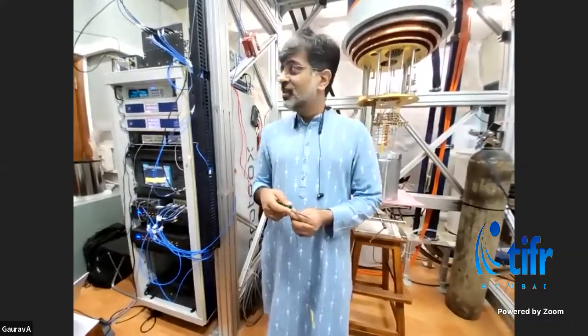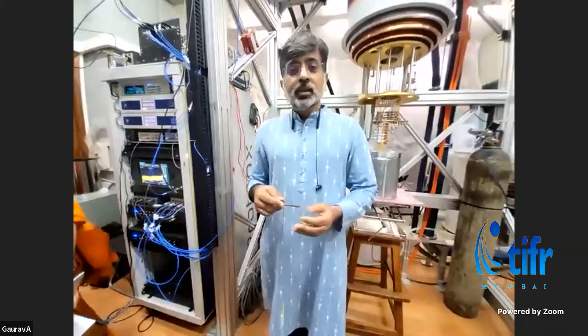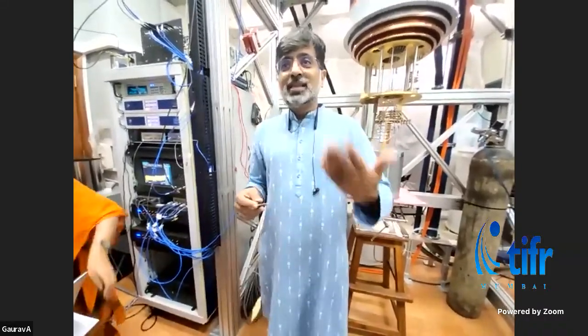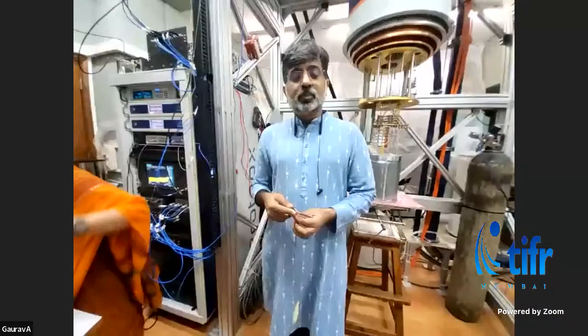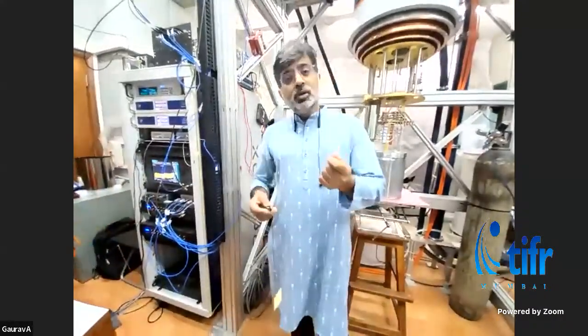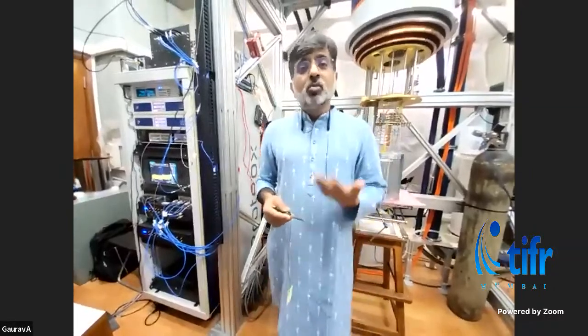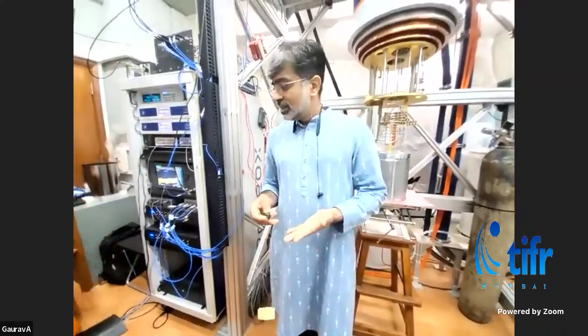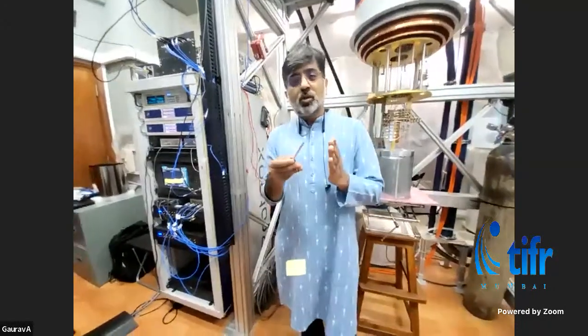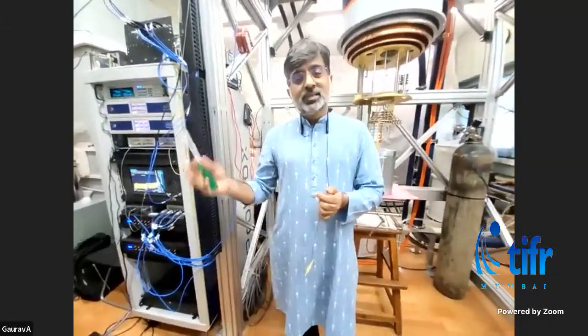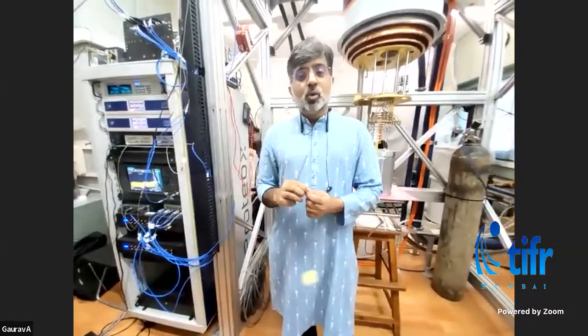And though things have been improving, just to give you a sense, in 1999, when the first superconducting qubit was made, the coherence time, or basically the time scale over which it decayed, was about a few nanoseconds. And now we're already at about 100 microseconds or so. And there have been experiments where people have approached almost a millisecond. This is important because when you're doing your computation, you don't want the system to decay, because then the computation is essentially garbage. So right now, the experiments have to be done in a very, very short amount of time compared to the time over which these systems decay. That's typically what we call the decoherence time.